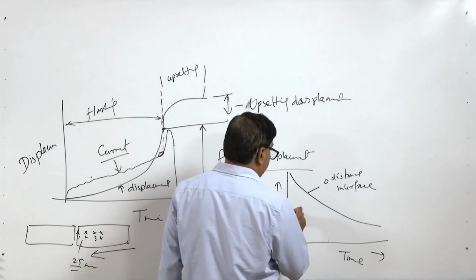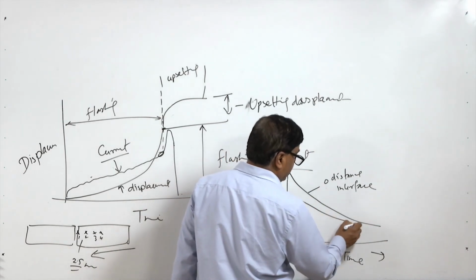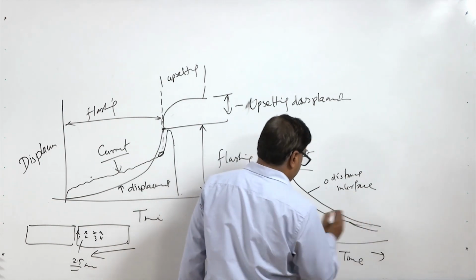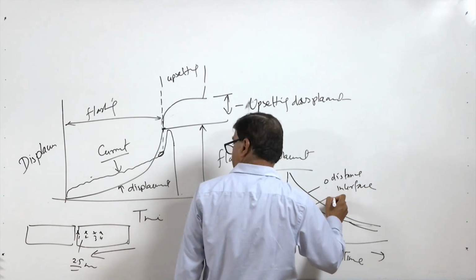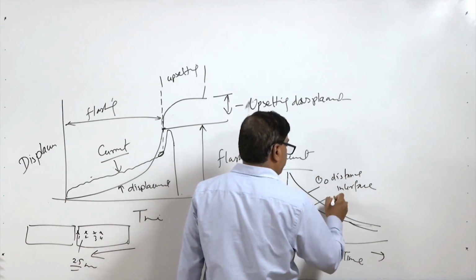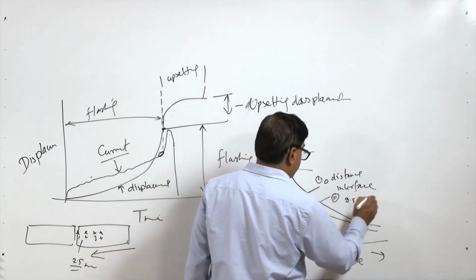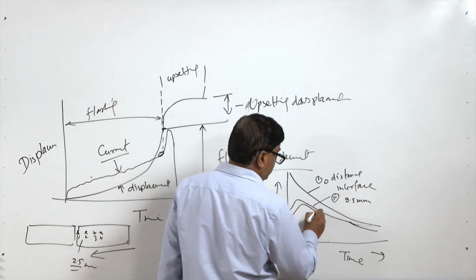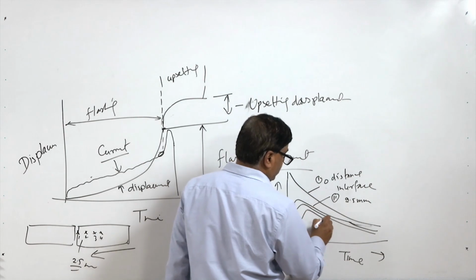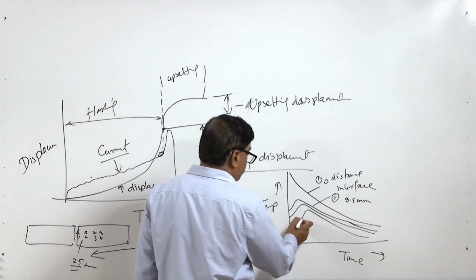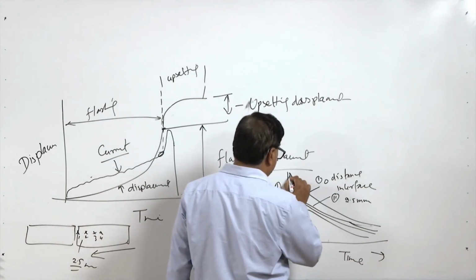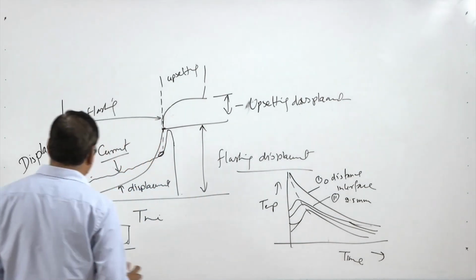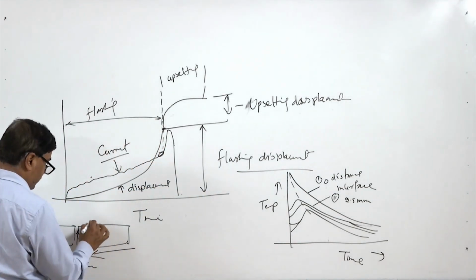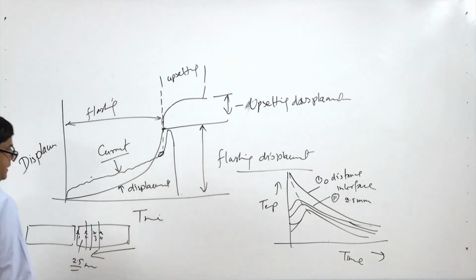experiences direct cooling, but the points which are away will experience a thermal cycle like this. This is point 1, point 2 at 2.5 mm distance, and then point 3 taking a somewhat longer period, point 4 further taking a longer period. So, the peak temperature and the time to reach the peak temperature are also longer. Depending upon the kind of metal system, the heat affected zone may be of different sizes. This is what we can see from the weld thermal cycles.